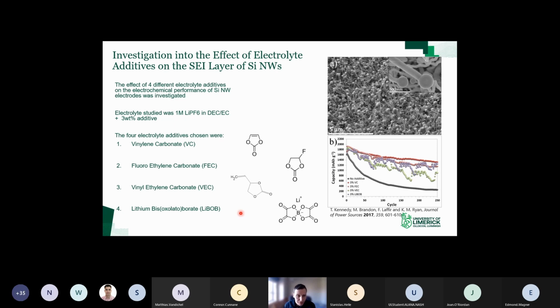When we coupled them with silicon nanowires, so these are 100% silicon nanowire electrodes, we saw that there was a huge variation in the performance. The VC outperformed all the rest by a margin. The FEC and the LiBOB performed similarly in terms of capacity retention, but for the LiBOB, you can see the data was not the smoothest, and VEC the same. The reason for that is related to the SEI layer, but those are temperature effects basically. As the temperature in the lab fluctuated, as the temperature went down in the lab, you get a reduction in capacity when you use those electrolytes, and when the temperature goes back to room temperature, it recovers. So nighttime temperature is low, you get a low capacity.